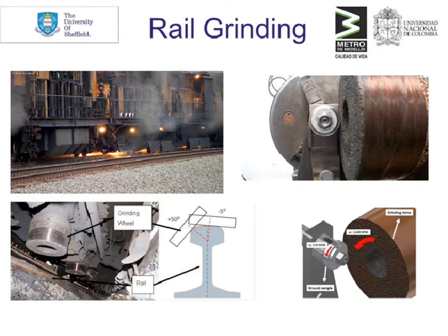You can see here the rig that the Colombians have built to allow grinding of our twin disc specimens, which means we can grind a sample, we can analyze it, but also we can take it away and carry out rolling sliding tests on it to see what impact the grinding has on subsequent damage formation.